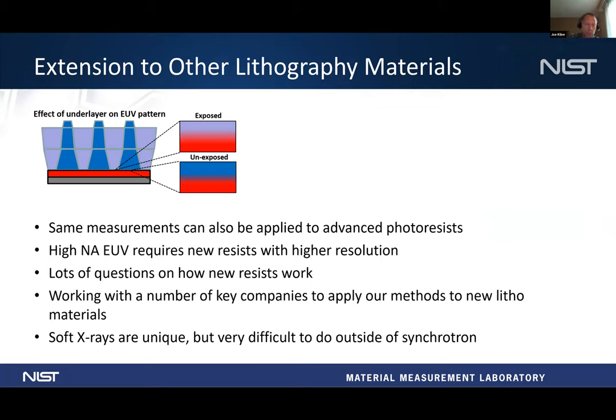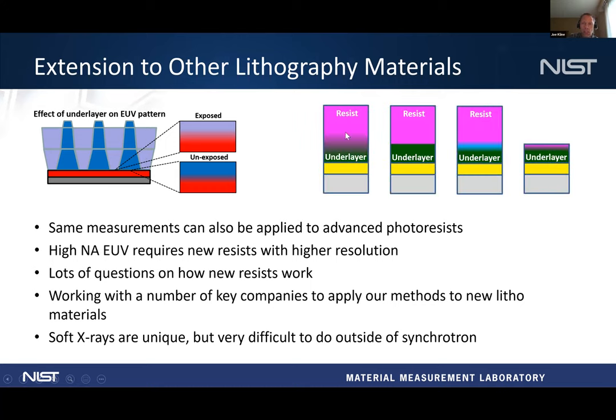And so for these same type of measurements, we're extending them now to look at EUV photoresist. So you can look at the photochemical pattern that's formed in the EUV resist from the EUV exposure before you do the development. And then there's also a lot of interest in how the underlayer interacts with the EUV resist. And so in particular, these are some of the different examples you could think about that might happen there, where you might have a lot of mixing between the resist and the underlayer. It might be sharp, or you could even have interfacial chemistry that occurs there.